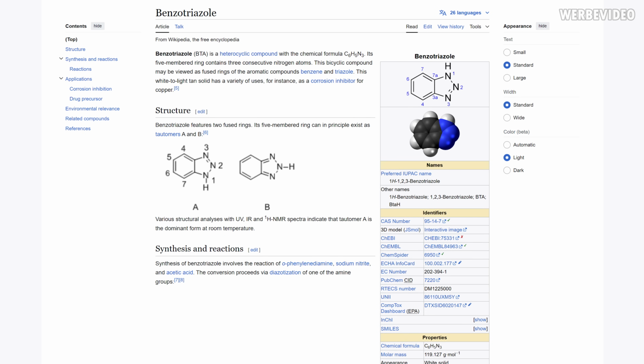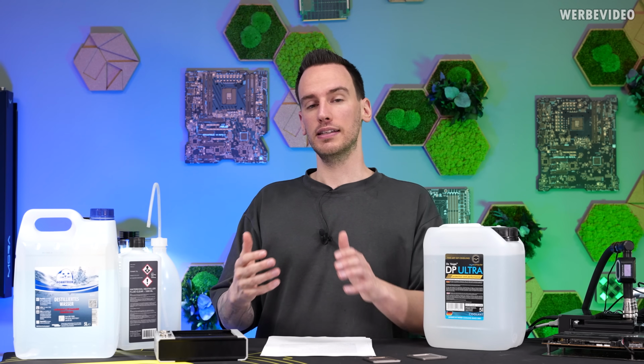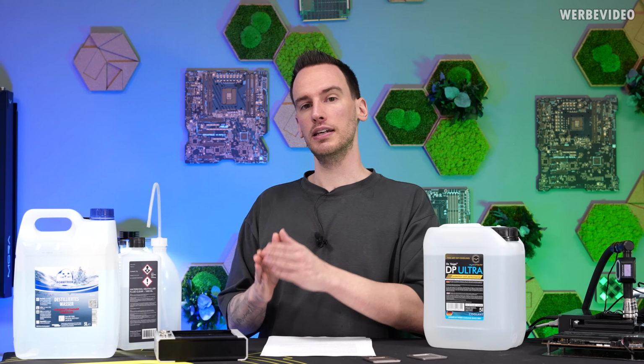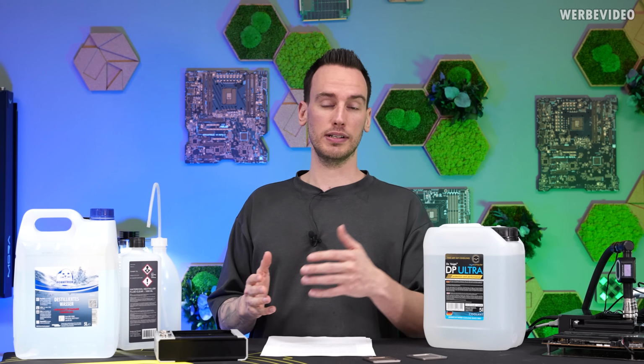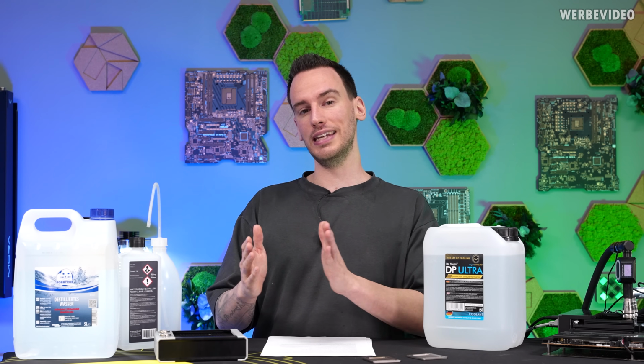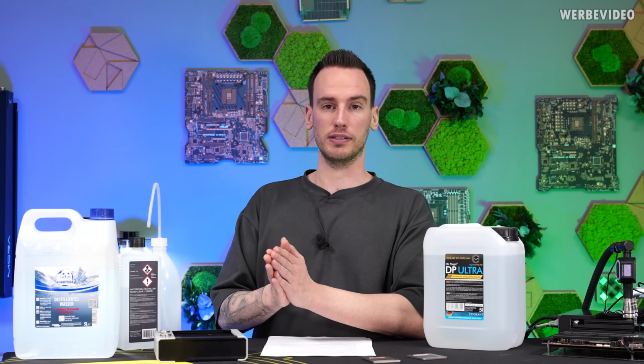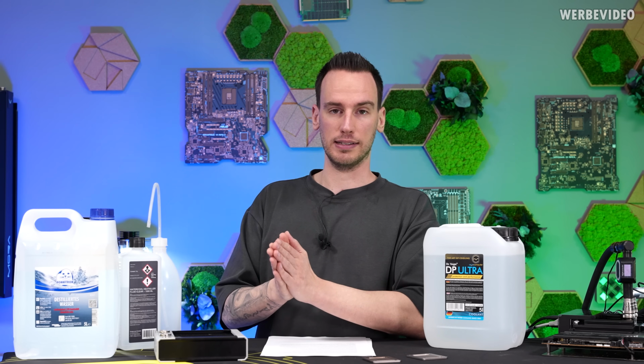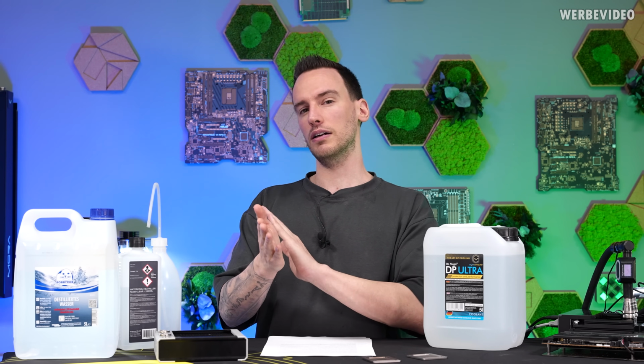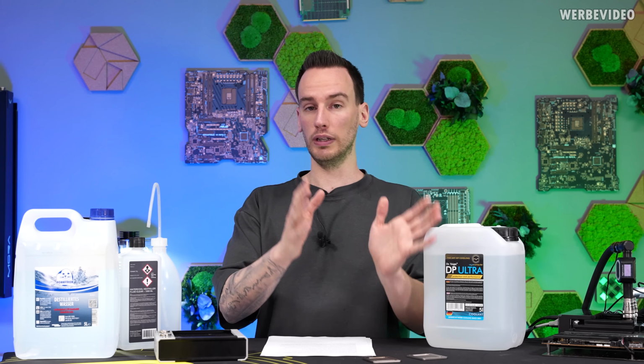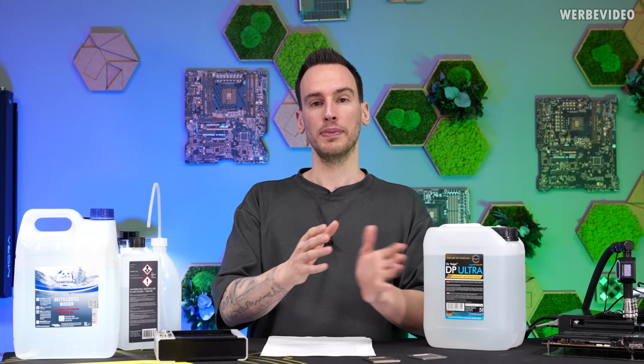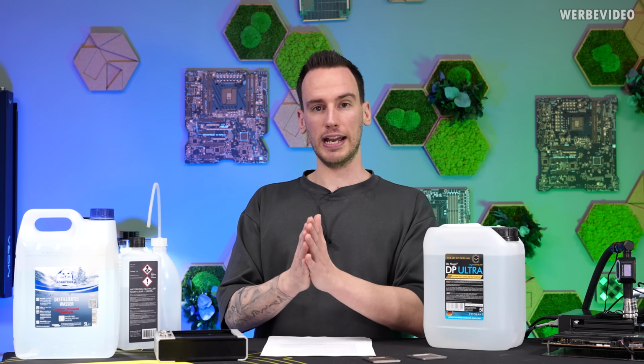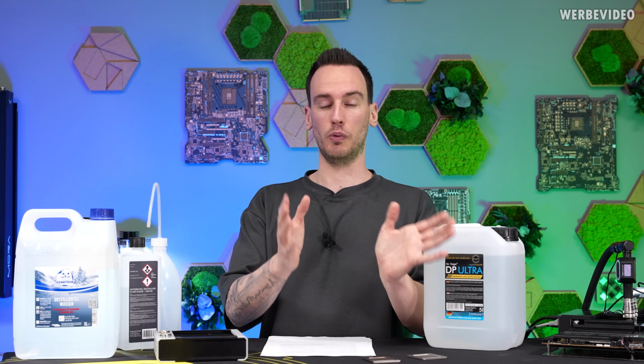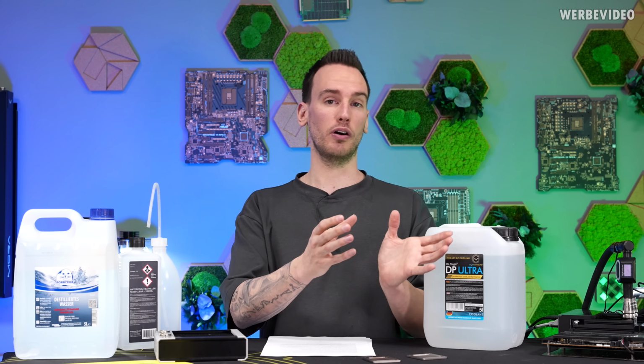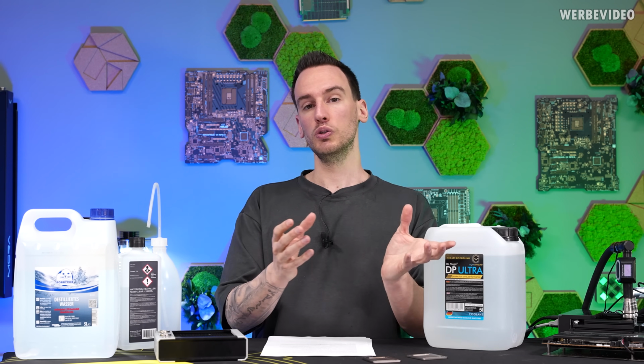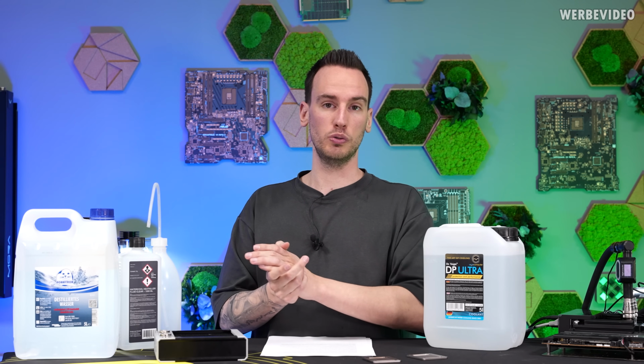It's a selective corrosion inhibitor. Inhibitor means that it's slowing down the corrosion. It doesn't fully prevent it, but it's drastically slowing it down. It works in the same way, in that the benzotriazole is sticking to copper-related surfaces. So that is anything that is copper or brass. And because it's creating like a monolayer in between the coolant, which is basically the distilled water, and your copper, there is no direct interaction, which makes it really hard for the distilled water to take up more ions, or also, if there are already ions present in the distilled water, to deposit them back onto other metals.